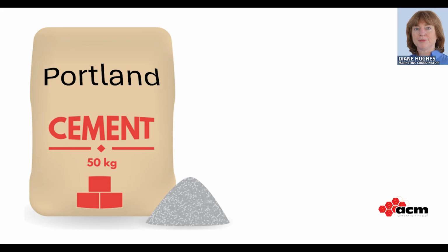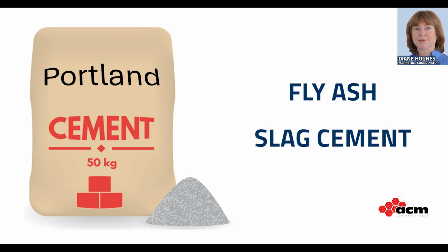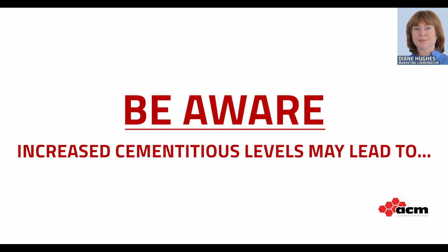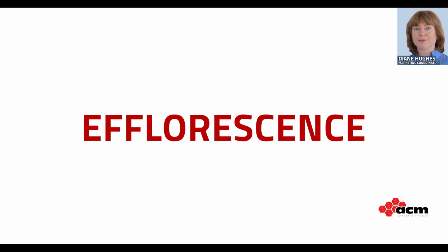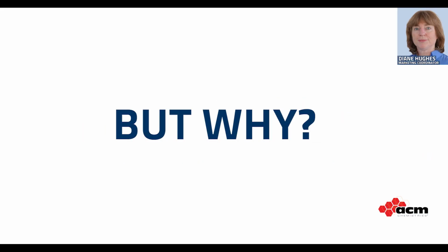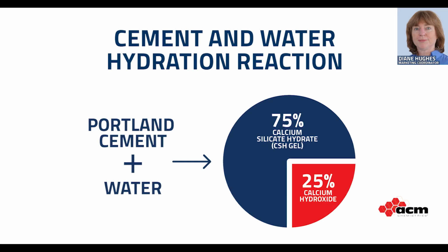Increased Portland cement and other cementitious materials like fly ash or slag cement can deliver many positives for pavers and slabs, but there is an important downside to be aware of. Increased cementitious levels may lead to increased potential for efflorescence. So why is this? Increased Portland cement means more cement hydration reaction with calcium hydroxide byproduct from that reaction. Calcium hydroxide is an important contributor to efflorescence production.